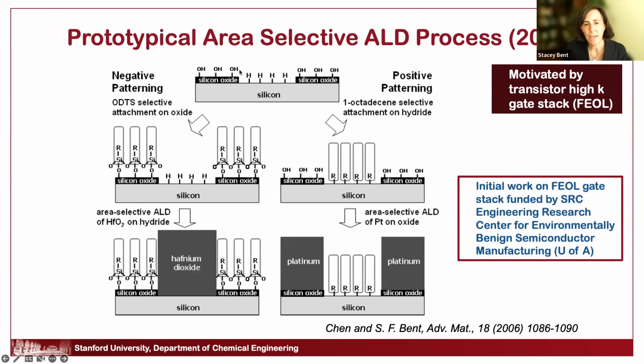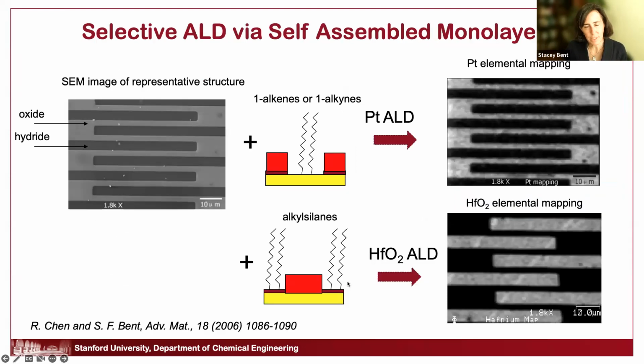And we had this idea that if you have your region here where you've got your oxide surrounding your silicon gate region, you would want to put down your high K material like your hafnium dioxide selectively on the silicon gate region. And we would do this by, again, using inhibitors that went down on the silicon oxide selectively and then hafnium oxide deposition. But at the same time, we thought, well, there's a way potentially to do the reverse selectivity where we would preferentially block the silicon and therefore get growth only on the silicon oxide. And it turns out that that process was developed and does work.